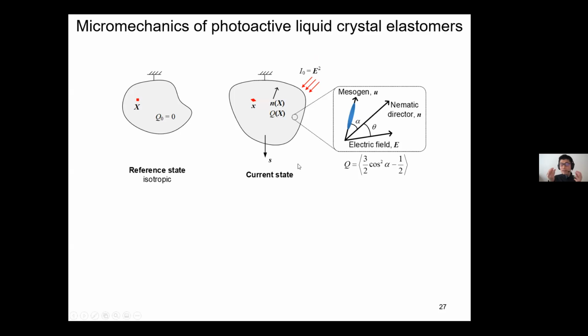So what's a little bit different from rubber elasticity is now you have an order parameter distribution, which gives you how well these mesogen molecules align with a certain nematic director. And then you have a field of nematic director basically at each element or REV, what is the direction of the alignment of these molecules?